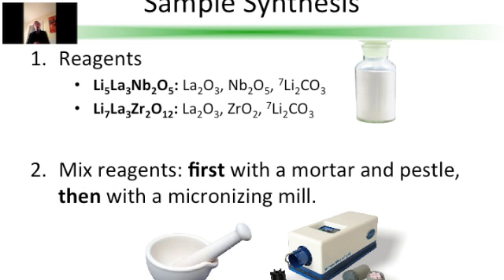Okay, so the first thing I would do is weigh the reagents in stoichiometry and then mix them with a mortar and pestle. To better activate the reagents, I later would mix them with a micronizing mill. And a micronizing mill is just a machine where you load your powder reagents into this canister filled with these solid cylinders, and you'd insert it into the micronizing mill, which would then shake the canister very vigorously, and because of that, the grinding between the cylinders and your powder reagents, you'd have a very fine mix.